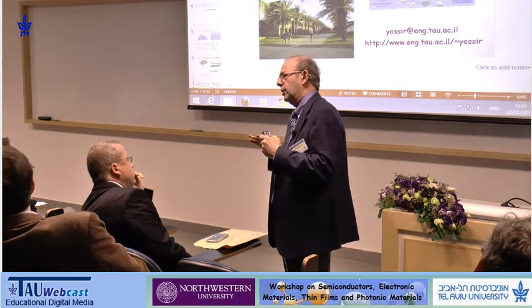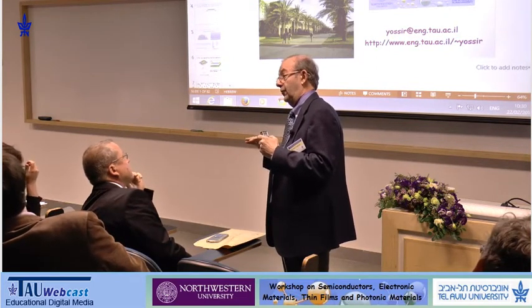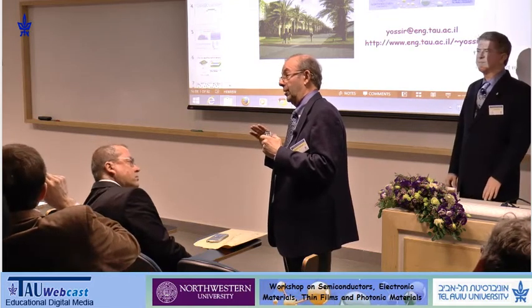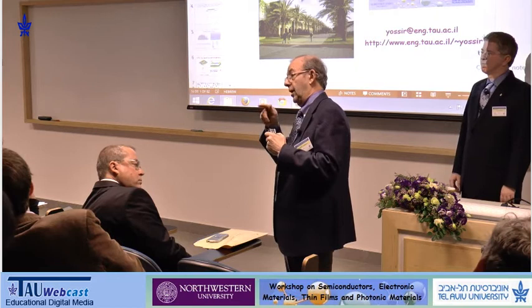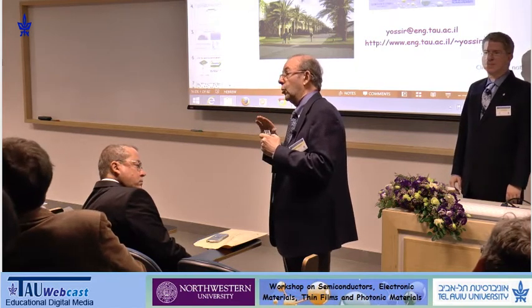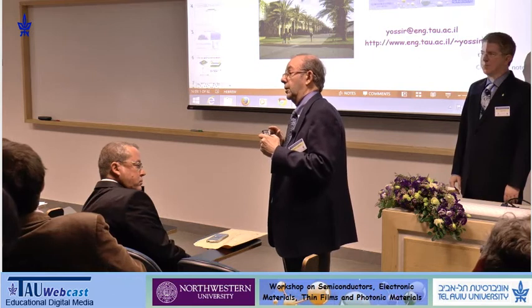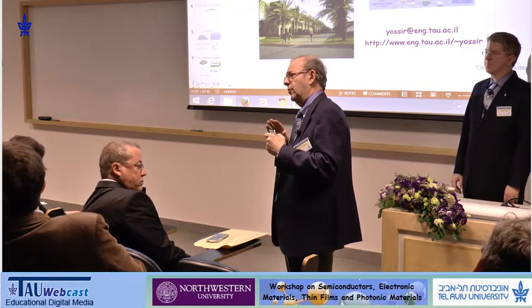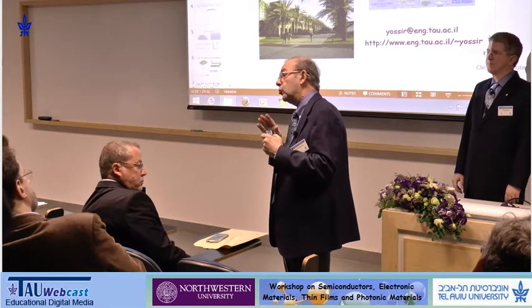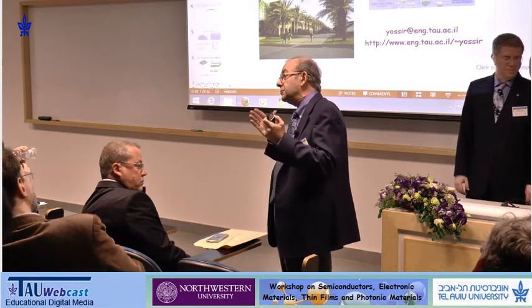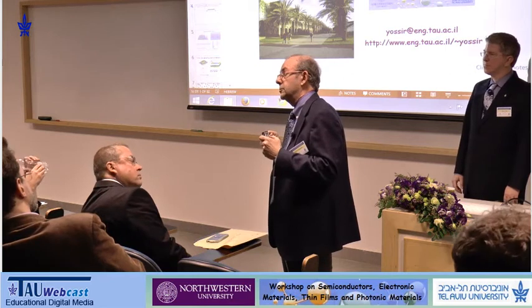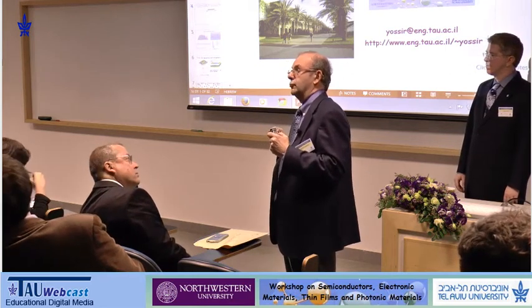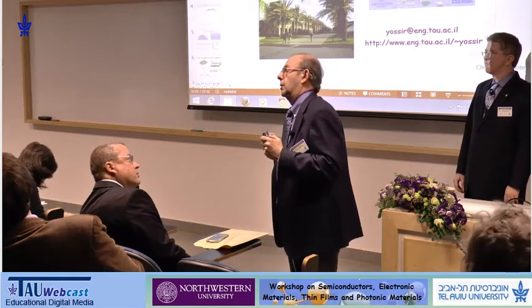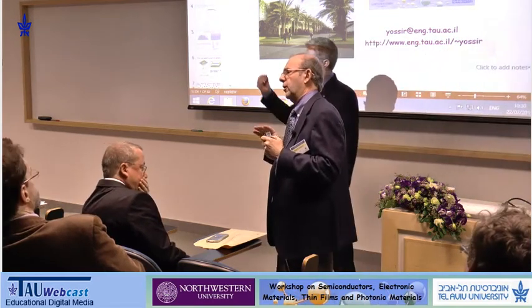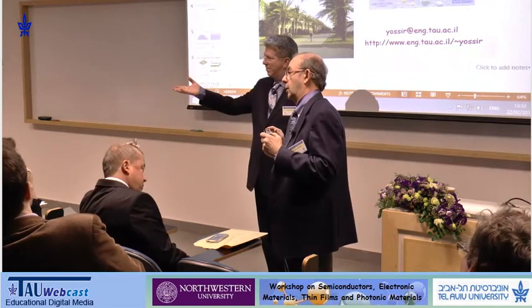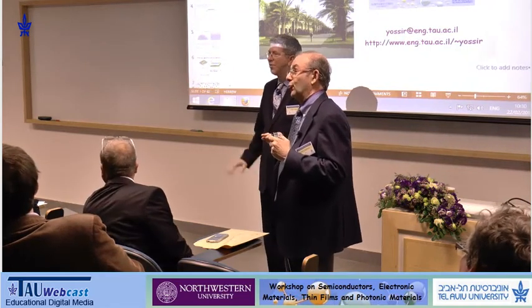And the positive point is that the density is correct for the areas that are a monolayer and 100% graphene. But for these areas that are kind of amoeba-like in shape, those are always deficient in carbon. Instead of being what graphene's around 36, we get around 32. So I'm just wondering if those amoeba-like regions are induced by the deposition, subsequent milling, et cetera. That would be hard to say. It would be hard to identify which one, in an absolute sense.